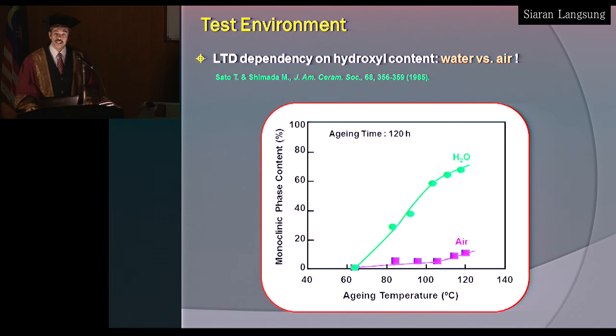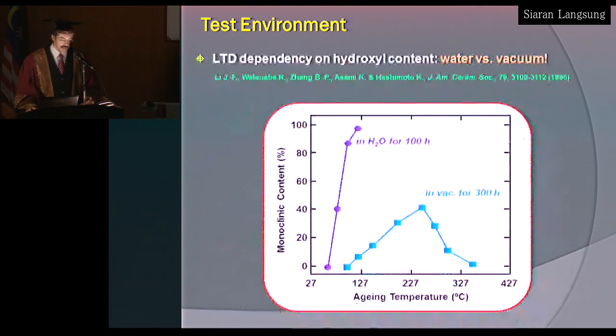Now the test environment has an effect as well. If it's fully water, then the degradation is rapid. The LTD responds to hydroxyl, so it is rapid as compared to air. In the same case, when it is exposed to vacuum, there is a temperature dependence as well, where phase transformation still occurs. But obviously in water, it is much more rapid.